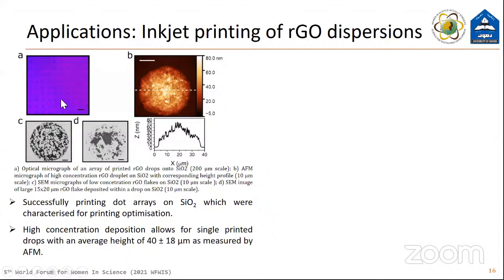As you can see in this photo, this is an optical micrograph of an array of printed RGO. In this case, it's RGO dispersion. We printed this onto a silicon wafer, and this photo shows an AFM micrograph of a highly concentrated RGO droplet on the silicon wafer. And this is the SEM image of low concentration, and an SEM image of a large area.